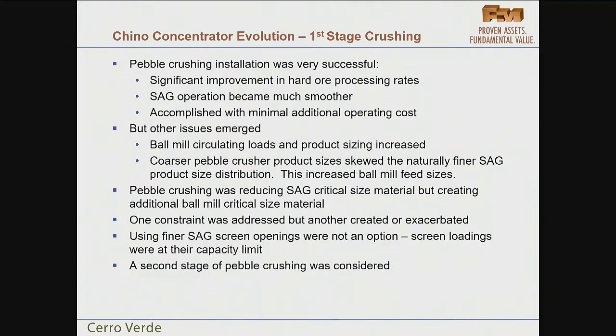Ball mill circulating loads increased, and the product size from the ball mills increased. What was happening was that the coarser pebble crusher product sizes skewed the naturally fine SAG distribution and increased the ball mill feed size. So we were using the pebble crushers to eliminate the SAG mill critical size, but we were creating ball mill critical size. Action and reaction. One constraint was addressed while another was created or exacerbated. We couldn't go to finer SAG screen openings because, of course, the SAG screens were overloaded. So what do you do?